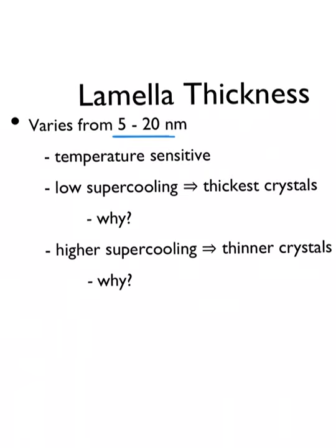And this is, of course, temperature sensitive. So the amount of energy present determines how thick they can be. And so with molten plastics, think of them as being on the 5 nanometer thickness. Okay, that's 50 angstroms. It's next to nothing. That's a bunch of air molecules strung together. So these things are very, very thin, very hard to see.